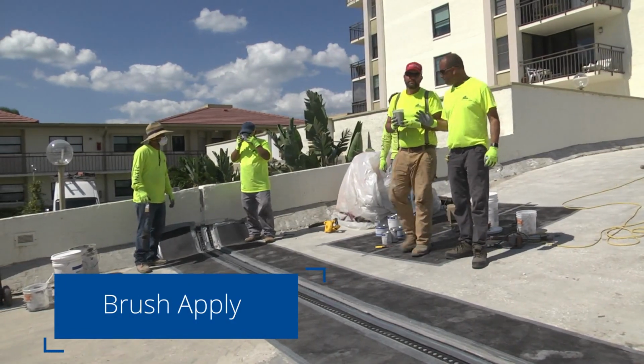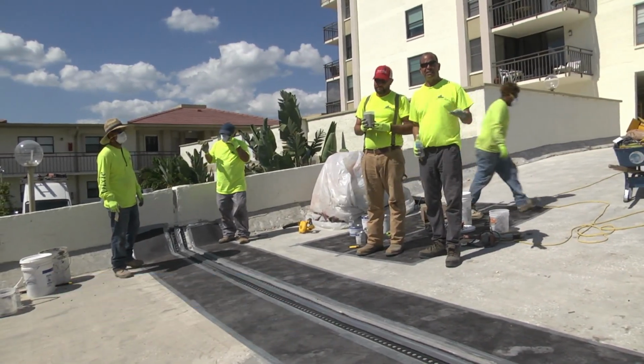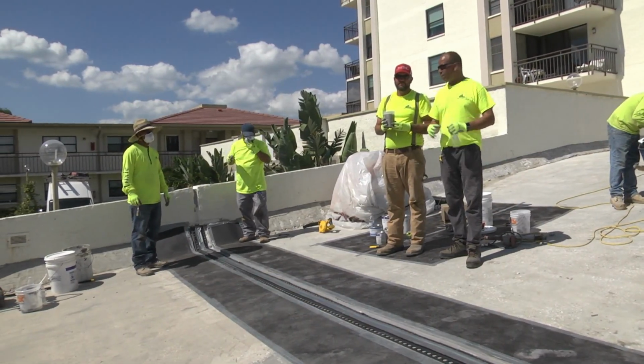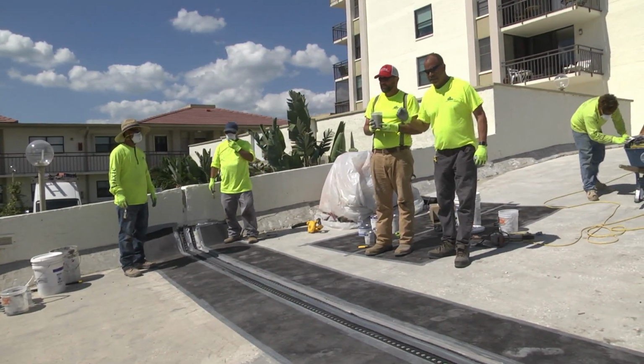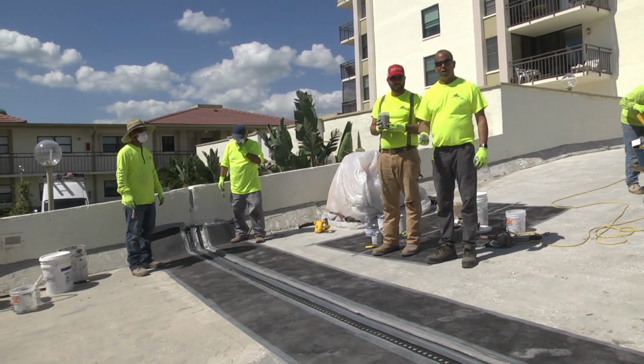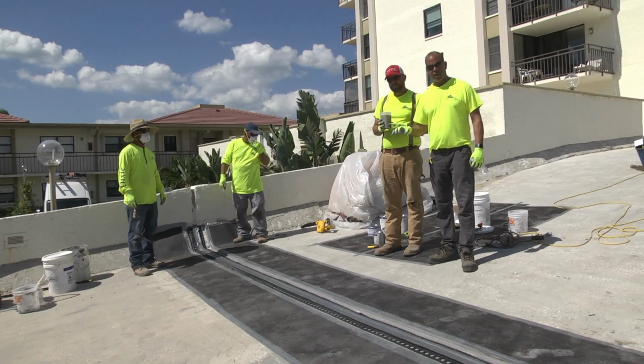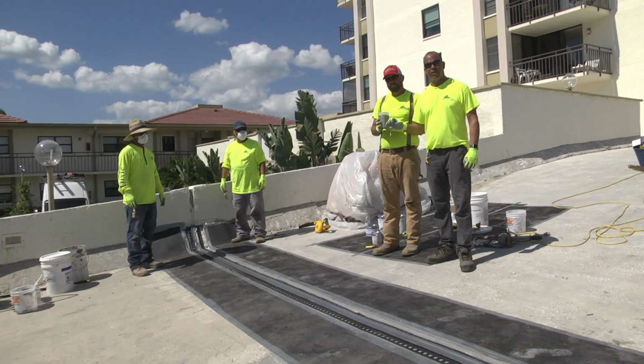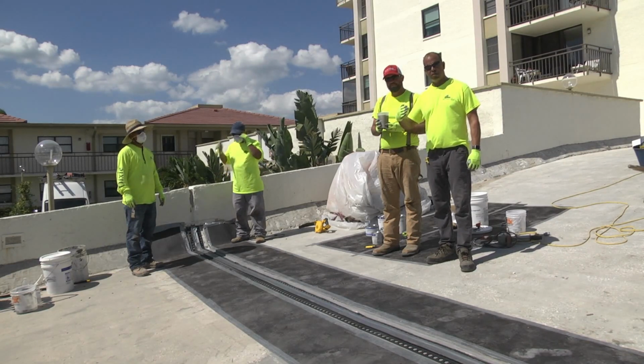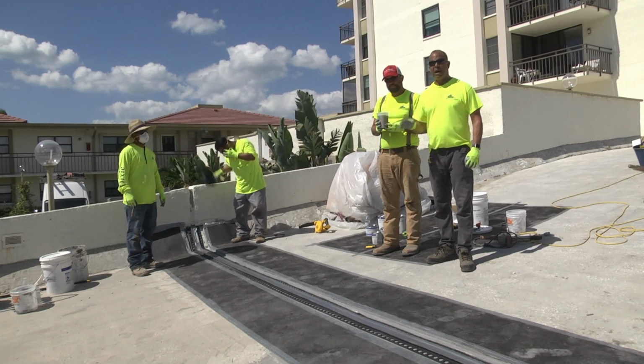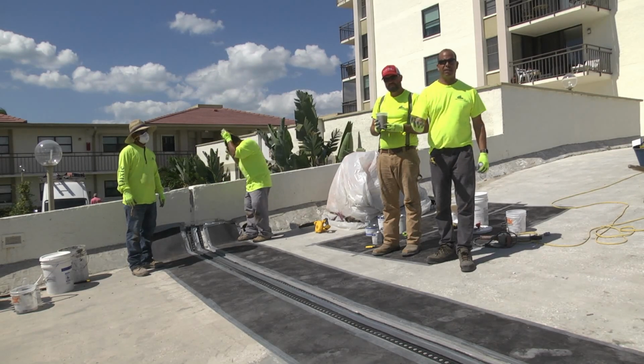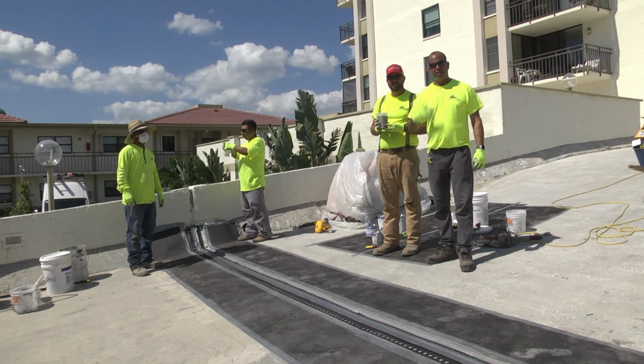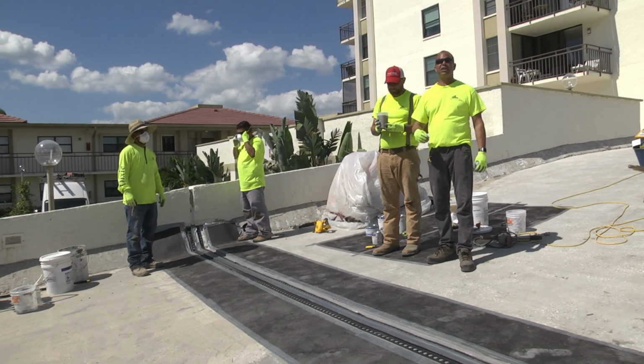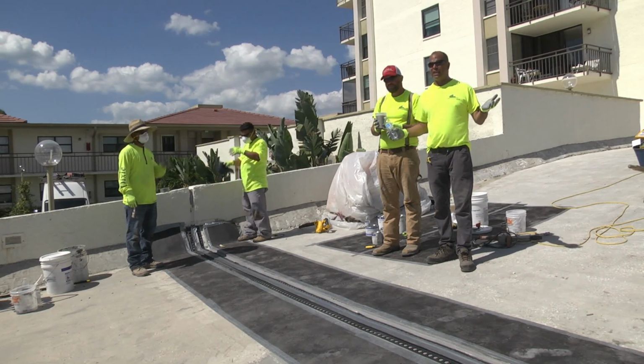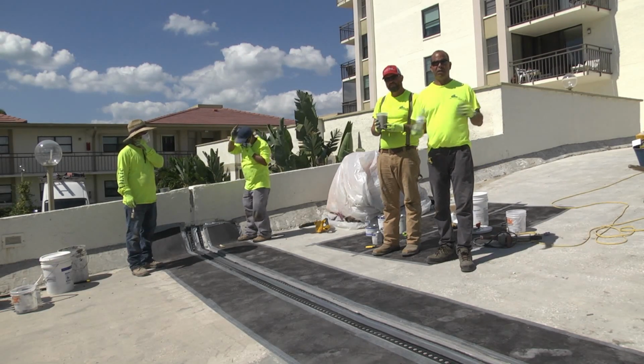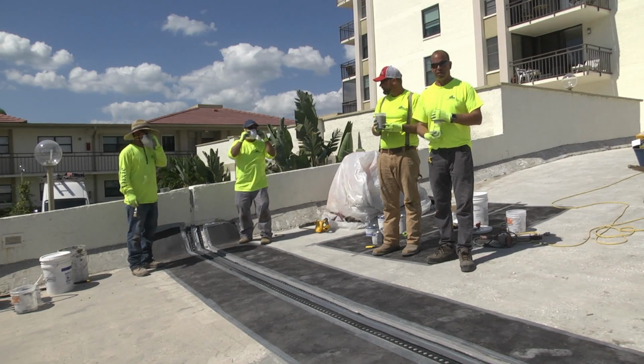So we've got our epoxy mixed. The key now, especially on a hot day like today in the 80s and the 90s, is to make sure you get it out of your container and get it into the blockout and put it down in a thin layer. What we're trying to achieve here is to prime the concrete only, not the rubber or the seal, the concrete only on the horizontal and the vertical. If you put it out in a thin layer, your working time increases dramatically. If you leave it mixed in a bucket, the exothermic reaction of the material kicks a lot faster. On a 90-degree day like today, we probably have about a 30-minute working time, which is more than enough for us to put this down.